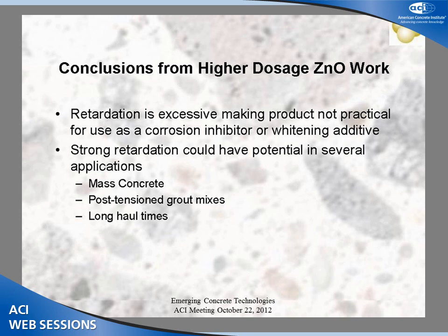So what were some of the conclusions that came out of the work? Well, retardation is quite excessive, which comes as no surprise based on seeing some of these numbers. So in and of itself, as it is right now, using zinc oxide as a corrosion inhibitor in Portland cement concrete, or to use it as a whitening additive, is not feasible, unless some smart researchers come up with a way to offset the retarding effects of the zinc oxide. As good of a corrosion inhibitor as it is, based on this research right now, there needs to be some way of formulating it to offset the effects of the retardation.